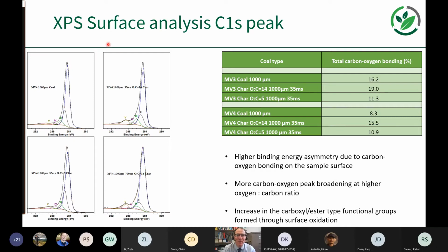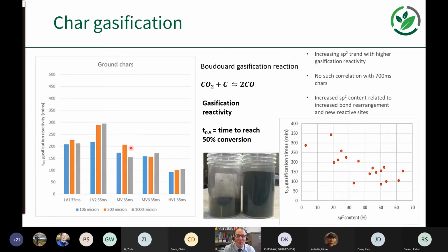On the surface, we've used X-ray photoelectron spectroscopy to analyze the surface chemistry and then correlate that with reactivity to try and improve that. And we've looked at the gasification reactivity of these partially burnt chars, because for these partially burnt chars, there'll be insufficient oxygen to combust those further in the furnace, so they have to react by the Boudouard gasification reaction then to generate more carbon monoxide.